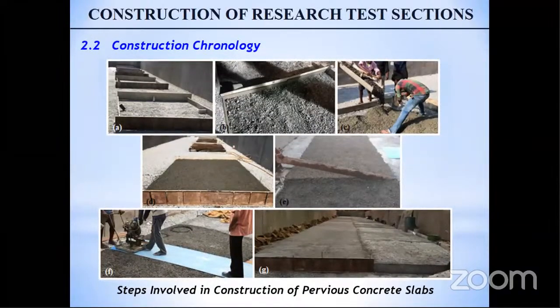Then again, as you see, panels were formwork was erected, and pervious concrete surface was laid. The basic difference between this study and the previous one was that in the previous study, in situ preparation method was used. But in this case, ready mixed concrete trucks were used, where the concrete was first prepared at a batching plant, and then it came to the site and was poured through RMC trucks. So this actually increased the rate at which the pervious concrete was constructed.